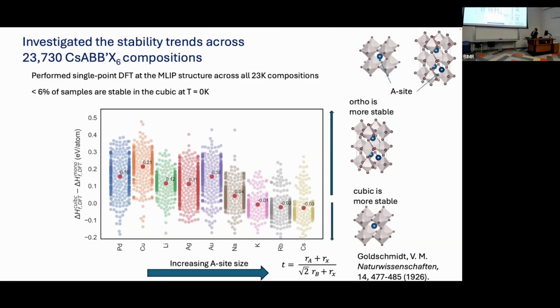So what you can see here is the difference between the energy of this cubic phase versus the energy of this orthorhombic phase. And the energy gets much larger as you decrease the size of the second A site cation. And that's pulling up the energy, which means that this structure becomes much more stable than this structure. So this confirms, or is consistent with, this Goldschmidt tolerance factor.